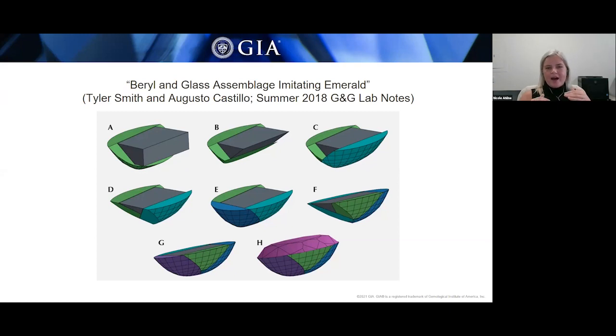First we have that gray box right in the center, and that's representing our natural beryl core. Then one side got attached with glass, as you can see by that lime green in the box labeled A. Then it was cut down a little bit to make room for that second glass segment, the teal that you can see in C. Again, it was cut down to make room for segment 3, the darker blue. The process was done one more time for segment 4, that purple. The final segment, presumed to be added last, was the crown, finishing up the creation of this very cautionary assembled piece that we saw.